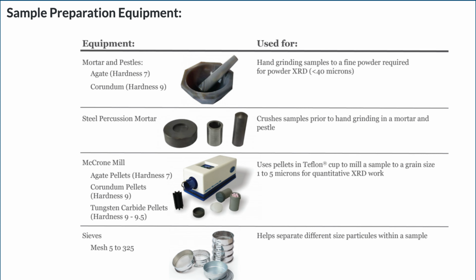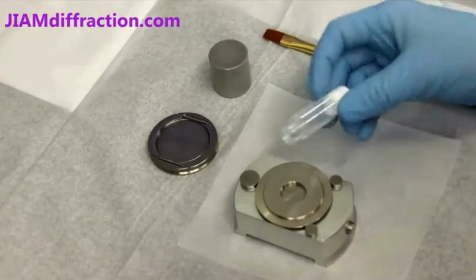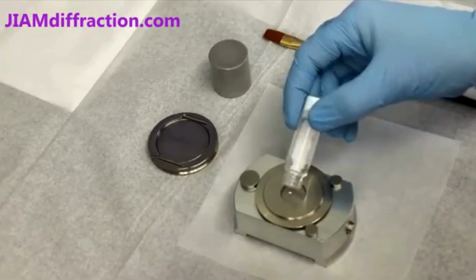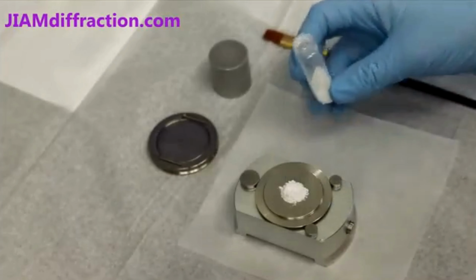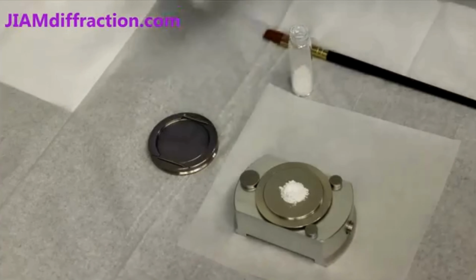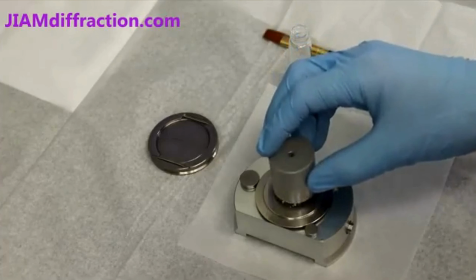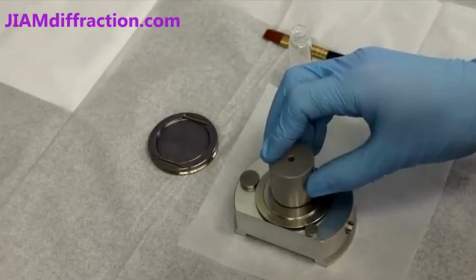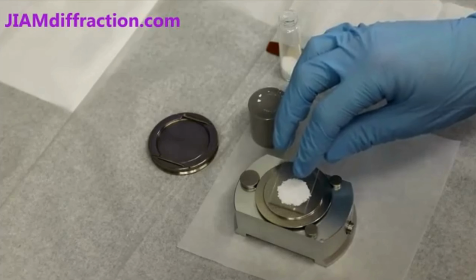Sample preparation and experimental considerations. Reliable XRD measurements depend strongly on appropriate sample preparation. Powdered samples are generally ground to particle sizes below approximately 44 micrometers to ensure random crystallite orientation and improved diffraction statistics. Fine powders typically produce sharp, intense peaks, whereas coarse or inhomogeneous samples yield broader and less reproducible patterns.